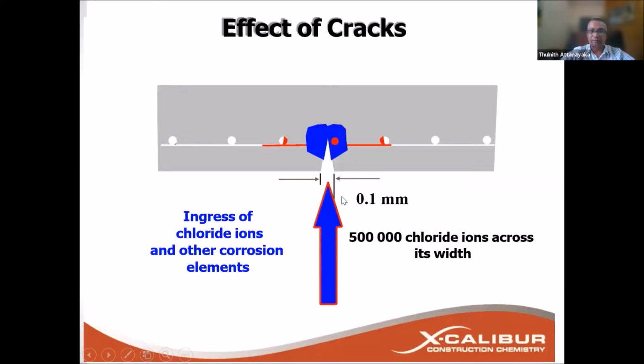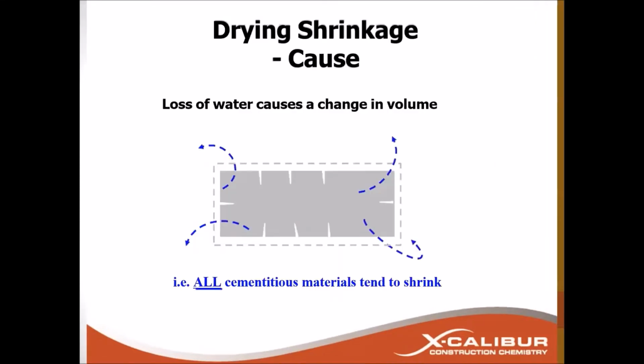We all know that concrete is porous. Normally designers allow 0.2 millimeter cracks. Even with a 0.1 millimeter crack, the ingress of chloride ions and carbon dioxide is possible. Let's say if you have a 0.1 millimeter crack, even 500,000 chloride ions can cross its width. So the cracks are very vulnerable, very critical to the structures.